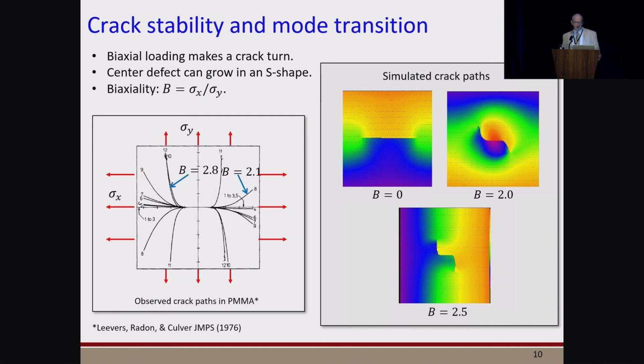Crack stability, similarly, is reflected in this autonomous crack growth idea. These are simulations of a brittle plate with a center crack in biaxial tension. So we're pulling both vertically, which starts the crack growth, and also horizontally. And if the horizontal stress